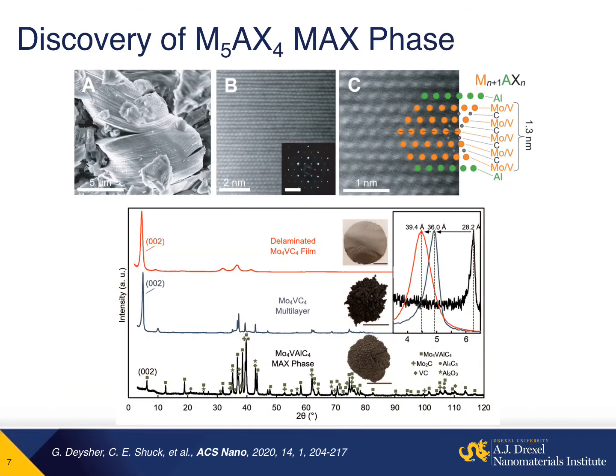When we looked at this material using a scanning electron microscope, we saw a structure that was very typical of MAX phases, so it's a highly anisotropic layered structure with some splitting. That's completely standard with MAX phases. However, when we zoomed in using a transmission electron microscope, we saw something a bit stranger. So I just want to point out from the selected area electron diffraction, it shows what looks to be a standard hexagonal P63/mmc structure, but looking at it very closely, you can see that it has this very unique herringbone-like twinned structure. So we've never seen this with the MAX phase before, where it occurs on one of the internal M sites. So this is a completely unique structure.